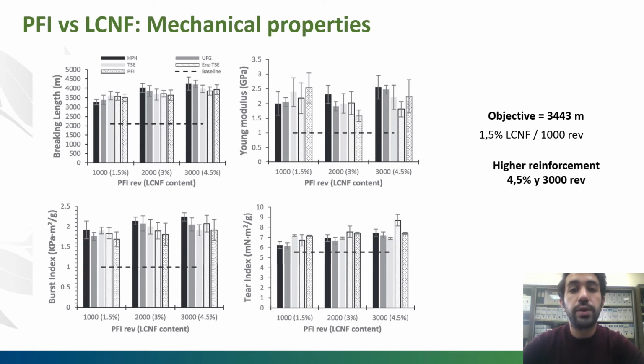If we observe, the values where greater reinforcing occurs coincide with this maximum amount or intensity of refining, producing reinforcement of more than 300% for the rupture length, Young's modulus, and burst index. However, the tearing index only increased by 30%. We can also observe that the reinforcing intensity is similar for both technologies, but when comparing treatments, small differences are observed, homogenization being the one that gives the best result due to the high aspect ratio that we commented on, followed by the ultrafine friction grinder, the Masuko, and finally the extrusion, but all of them very close values.